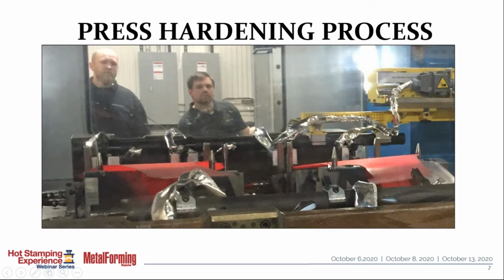The material itself, once it's heated to approximately 930 C, becomes very hot and sticky, much like a stick of chewing gum. So the coefficients of friction are 35, 40, 45%, which makes it very challenging in the tool to properly form the part and also to protect the tool over the life of the tool. But the material is very soft and flexible, which makes it ideal for making deep drawn parts. And that's where the biggest benefit of the hot stamping process is, the ability to combine multiple parts into one deep drawn part. That's where people see the biggest opportunity for weight reduction, mass reduction, and cost reduction as well.